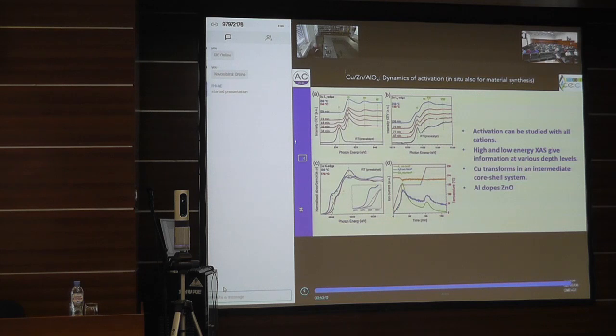And then you think, now, you take the zinc oxide and charge it with CO2, what will happen under reaction conditions? Of course, the zinc carbonate will form again. That means the interplay between zinc carbonate and zinc oxide that you see in this diagram number B is also a descriptor for the function of this catalyst, and you begin immediately to understand why this zinc oxide is a co-catalyst in this system, because it prevents the copper from being oxidized from the water, and it takes the CO2 and forms first a carbonate intermediate that can be more easily reduced than the CO2 by itself. That would probably not stick on the surface. So that's a lot of things that we learn from this.